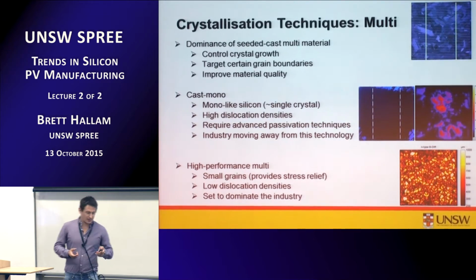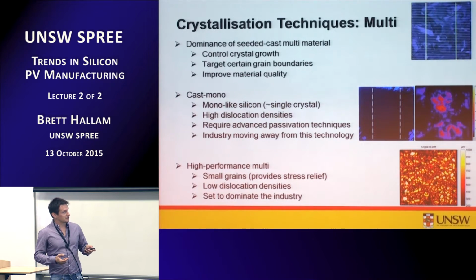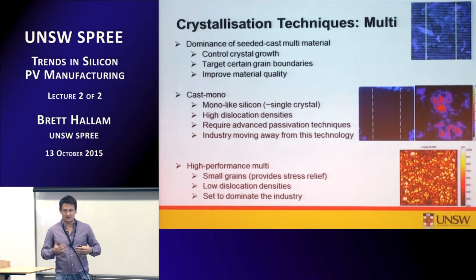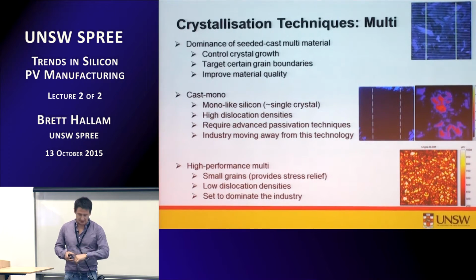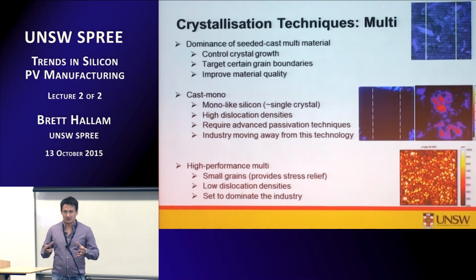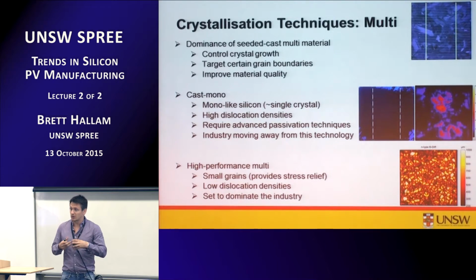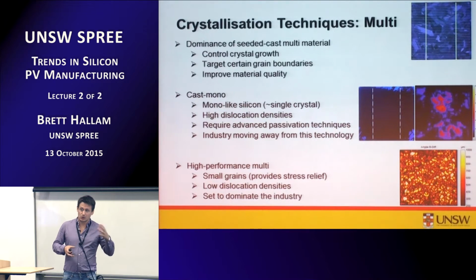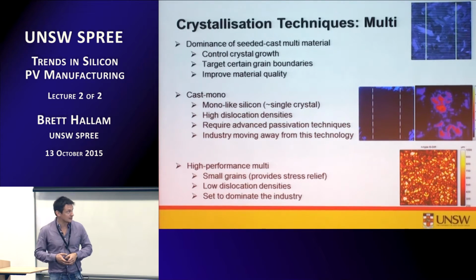grain boundaries act to eliminate the stress during the crystallization process, so they can minimize the generation of these dislocation clusters. And even though they have these grain boundaries, this is before they've given a passivation process during firing. For this crystallization process, they deliberately target certain orientation of grains in the silicon, and they choose grains that are lower recombination active in terms of their grain boundaries, so that either they won't hurt the solar cell performance too much, or they can be adequately passivated, say by hydrogen, etc.